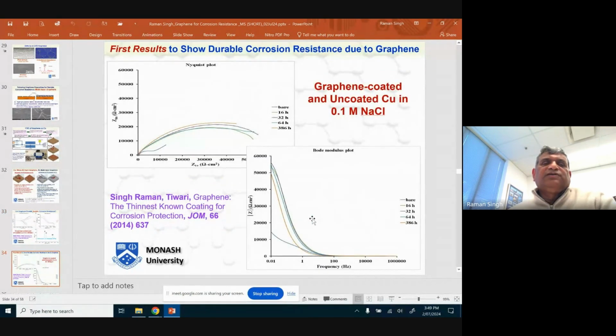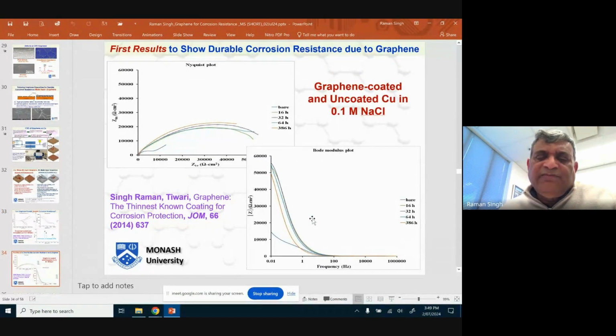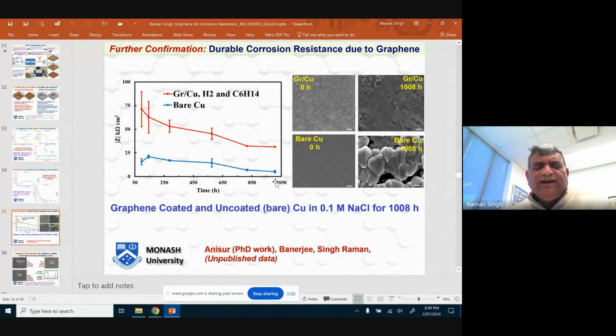But the most important thing is that for the first time we could show that whatever improvement in corrosion resistance happened because of this multi-layer graphene, that sustained for 400 hours. That was the entire duration of the test in sodium chloride solutions. For the first time, we could show that if you address the problem of discontinuities or defects in graphene, you can have long-term corrosion resistance. My other student, Anisur, also worked and he could show that the improvement can last for more than 1,000 hours and can continue. We did microscopy to prove that.